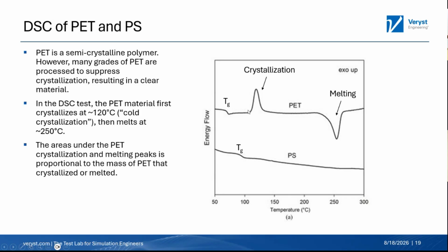And as we add essentially enough thermal energy to the system, the polymer chains are able to move around much faster. And when they're able to move around much faster, they can find the orientation where they form those crystalline domains. And you measure that as, in this case, an exotherm in the DSC trace. That actually releases heat. So basically, as we heat this up, we are allowing the kinetics of that phase transformation to be fast enough so that it happens on a relevant experimental timescale. Now, as we keep heating the PET up, we reach the melting point, and all of those crystalline domains are going to melt. And so if you take the area under these curves, then you can use that to calculate the degree of crystallinity in your PET material.